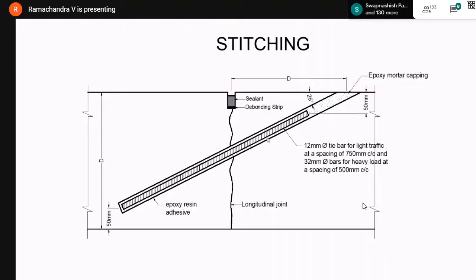Now, earlier you have heard of stitching cloths. If there is a crack, you stitch the cloths. Very similar to that, you can stitch the pavement also. If there is a full depth crack like this, what is done is you make a groove at some 30 degrees angle to the horizontal, make a groove like this across the crack, insert a bar and fill epoxy resin into this as an adhesive. You can put a 16 mm or a 20 mm bar, though a 12 mm rod is more than sufficient. A 12 mm tie bar rod, same thing you can add, and you can grout it with epoxy resin as an adhesive. That will ensure that these cracks are closed and that will not give any further problem.